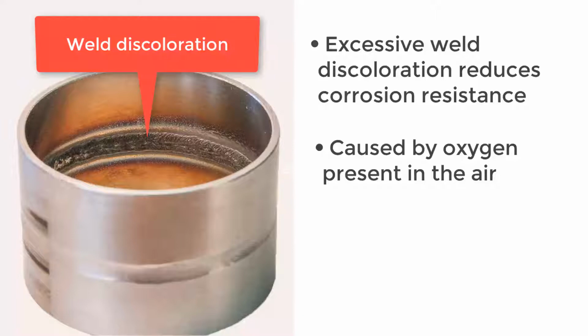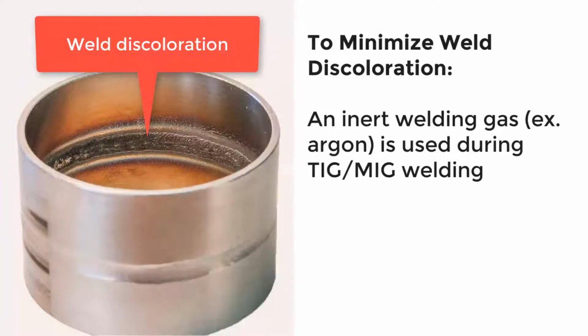During welding, the hot stainless steel surface reacts with oxygen in air, producing a non-protective high-temperature oxide. In order to minimize weld discoloration during TIG and MIG welding, an inert welding gas, typically pure argon, is used to displace air and thus oxygen.